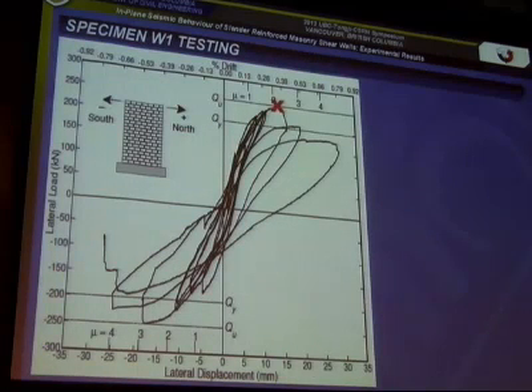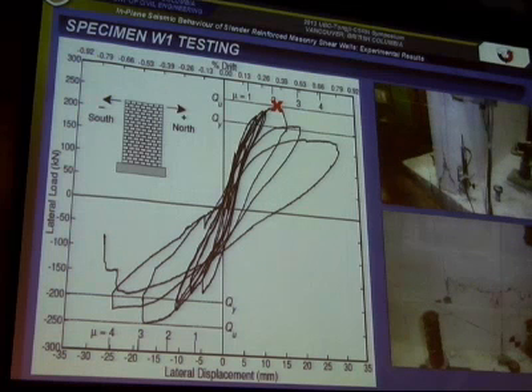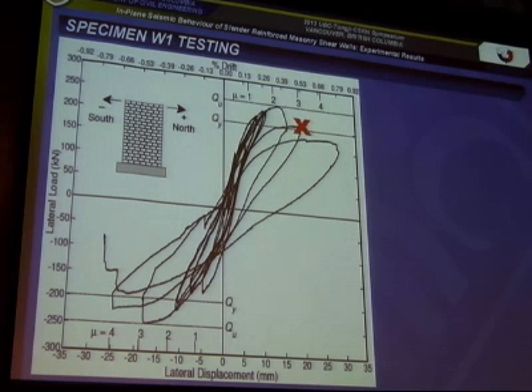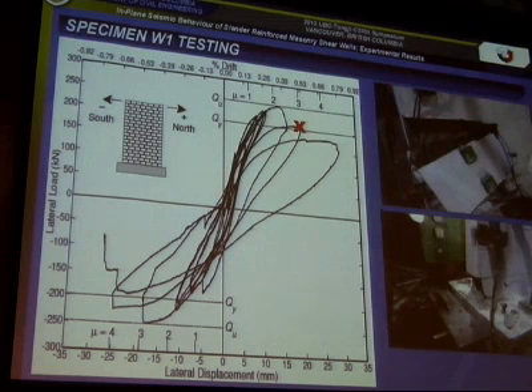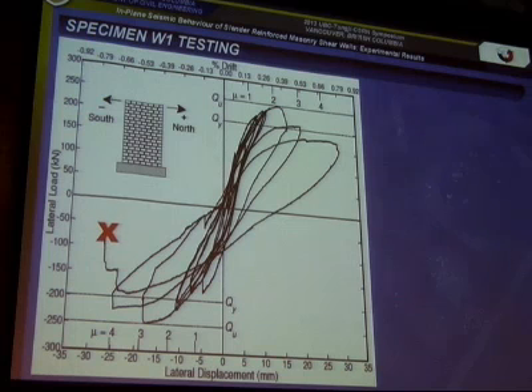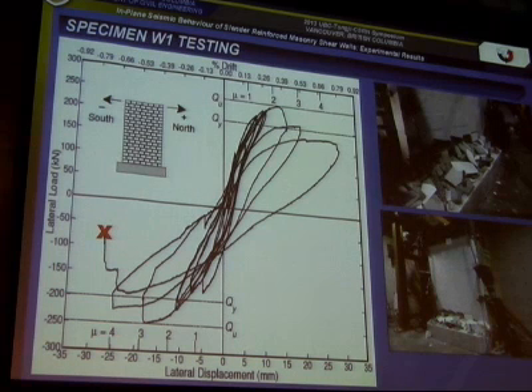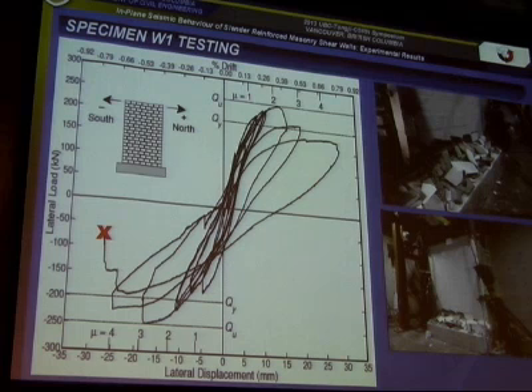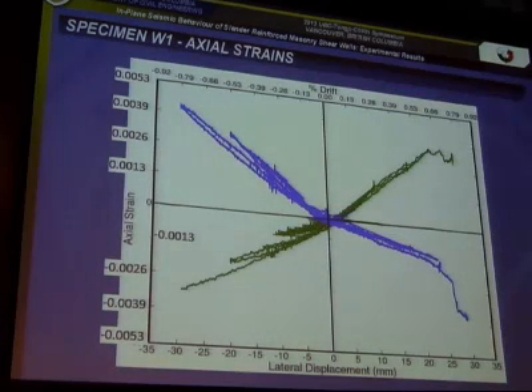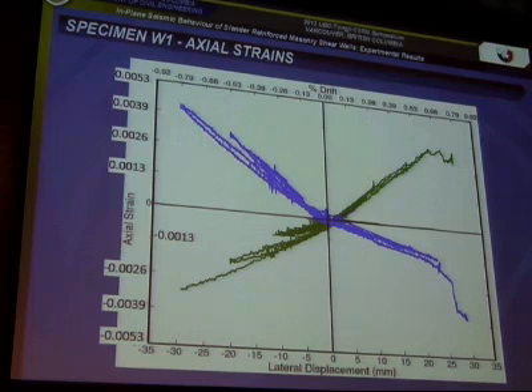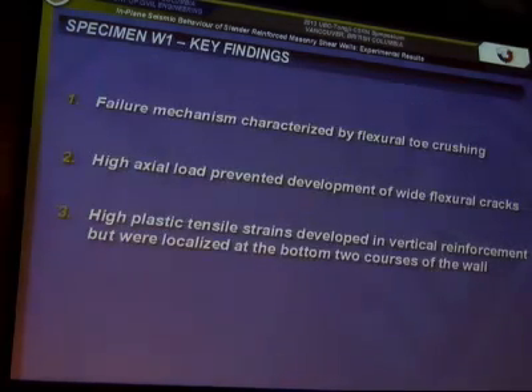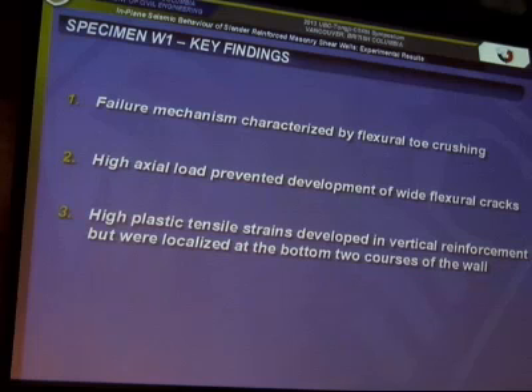Looking at the response, you can see that it's fairly elastic until we had some splitting and toe crushing at this north end. And this continued on with additional face shell spalling and crushing at the toes, until eventually we had a compression failure, but it was after significant damage that occurred at the toes. So looking at the axial strains, which were determined to be quite important, we had around 2 times the yield strain in the most exterior reinforcing bars at the failure. So our key findings were that the failure mechanism was actually toe crushing.